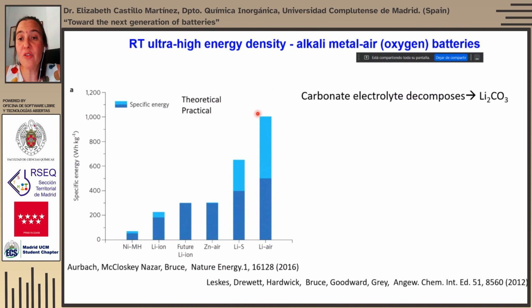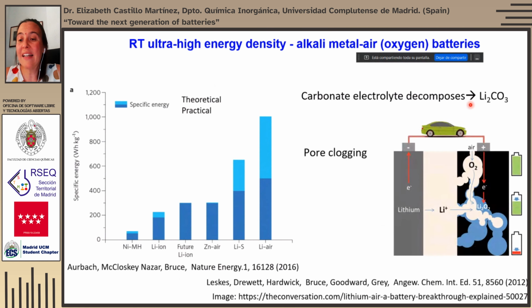Some issues related to this chemistry are that in the presence of liquid electrolyte, the previous example was with polymeric electrolyte, there is electrolyte decomposition, and this reaction, of course, is not reversible. And also the lithium peroxide is clogging the pores, and then when you want to bring the lithium peroxide back into oxygen, you have an issue because the electrons are coming from the carbon. You start by oxidizing the lithium peroxide in contact with the carbon. Once this is all oxidized, the remaining lithium peroxide gets disconnected from the carbon, and therefore you have lots of dead weight, which is not reversible.